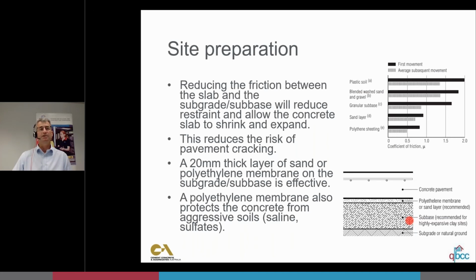And also the polythene keeps the water in the concrete and directs the water up as bleed water, which is a good thing. You don't want the water all sucked into the dry ground. So if you don't use polythene, it's probably a good idea to wet that ground down prior to the concrete going in, just to make sure that ground doesn't take the water out of the concrete.